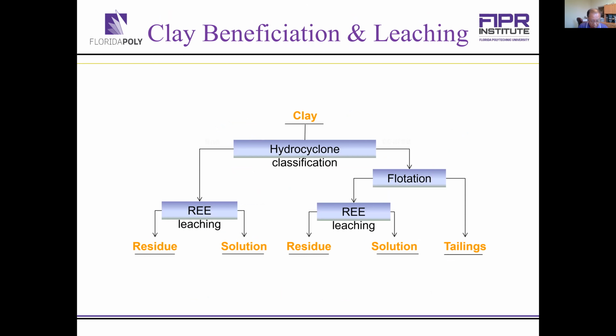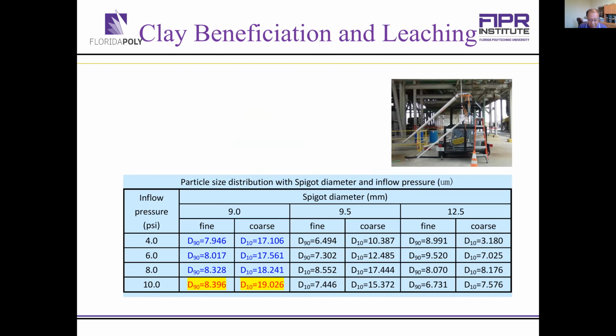So we did some clay separation using hydrocyclones of different diameter, and then used a flotation process to concentrate the underflow product and then acid leaching to recover the rare earth elements. We did an in-plant testing using a pilot scale hydrocyclone. So we tested 4-inch, 2-inch, and 1-inch hydrocyclones. As many of you know, the smaller the cyclone, the finer the cut size. We need to cut around 5 microns or less. So small hydrocyclones are required for this type of work.